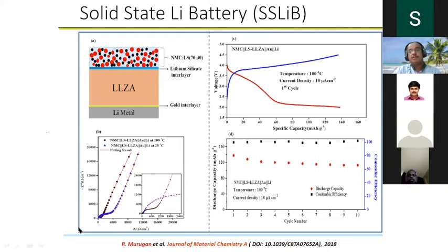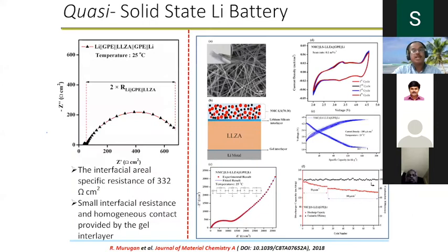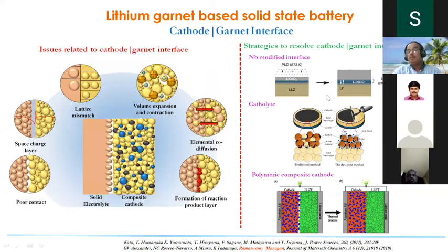You can see the battery performance with the lithium silicate interlayer. We are able to improve it compared to without lithium silicate, which is very poor, but we are able to show a few cycles. Then in quasi-solid-state batteries, people started to use a gel interlayer here and there, anywhere, so they're able to improve the performance. People are working on this at present; the glassy interface between the cathode and garnet is highly optimal. But much more interesting, we are living in the world of catholyte. Just mixing ionic salts with the composite cathode, you can make a toothpaste-like paste, then sinter it. The bonding is quite good, then high temperature starts to melt it and slowly bond.